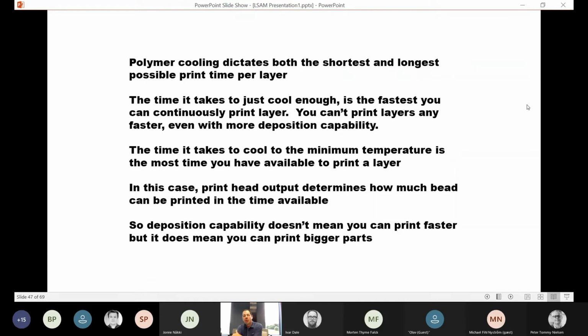So, polymer cooling dictates both the shortest and longest possible print time per layer. The time it takes to just cool enough is the fastest you can continuously print a layer. You can't print layers any faster, even with more deposition capability. The time it takes to cool to the minimum temperature is the most time you have available to print a layer. In this case, print head output determines how much bead can be printed in the time available. So deposition capability doesn't mean you can print parts faster, but it does mean that you can print larger parts.